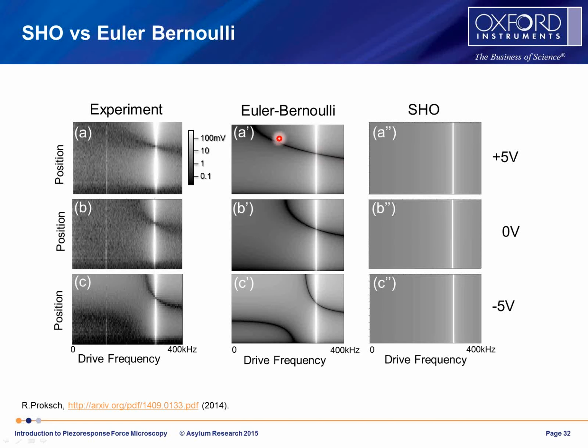And you can see that at least qualitatively, the Euler-Bernoulli model repeats that evolution really nicely. Even this little feature here is reproduced in the experimental data. Of course, since the simple harmonic oscillator doesn't include that spatial dependence, there's not much of a change in this. In this case, the electrostatic interaction was actually quite small. But it is notable that it was required to move to this Euler-Bernoulli model to explain that. The simple harmonic oscillator doesn't quite cut it in this case.